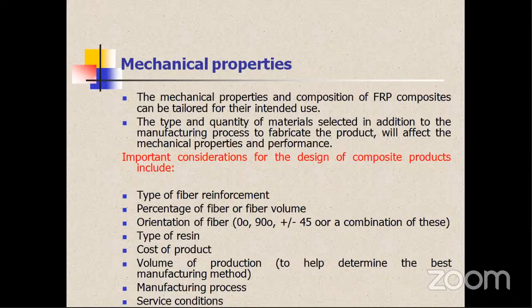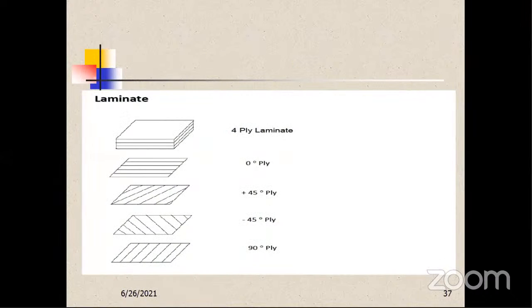Then what fabrication process you follow, and what service conditions the product may finally face. Those aspects you have to go into in depth before selection of either reinforcement or organic filler or inorganic filler, so that you can develop a multi-phase composite with either thermoset or thermoplastic composite. As I said, in classical lamination theory, orientation of each fiber is very, very important. That schematic diagram I have shown with different layers. In a composite, based on the bending properties required for the laminate, you can think of various architectures of fibers, so the stacking sequence differs.